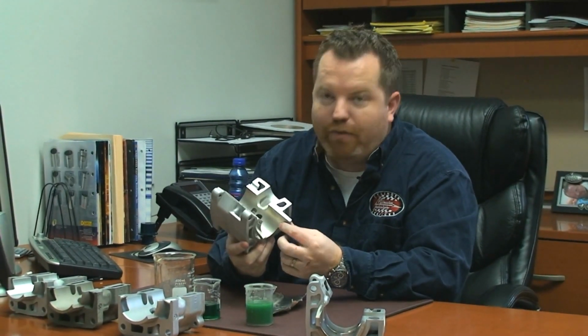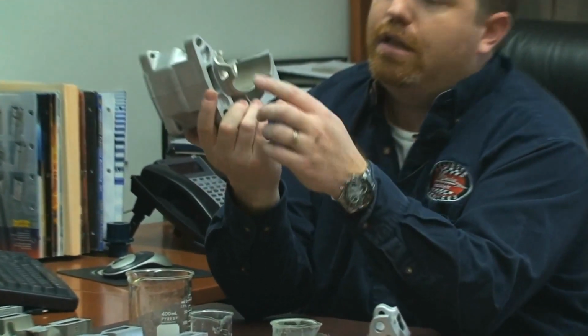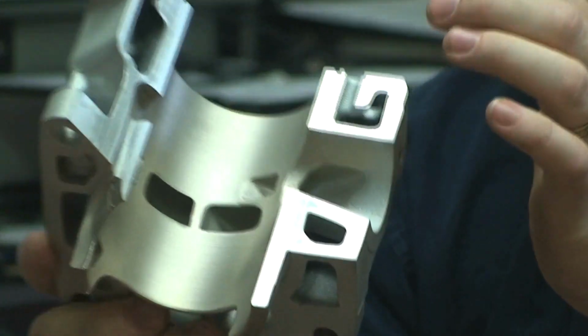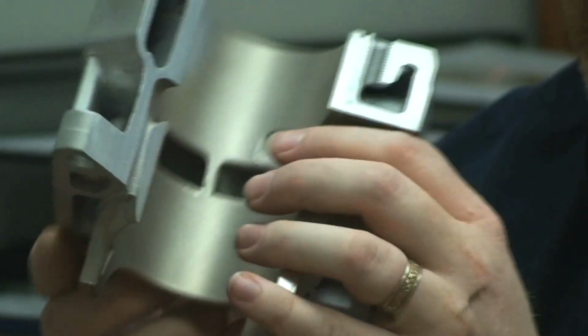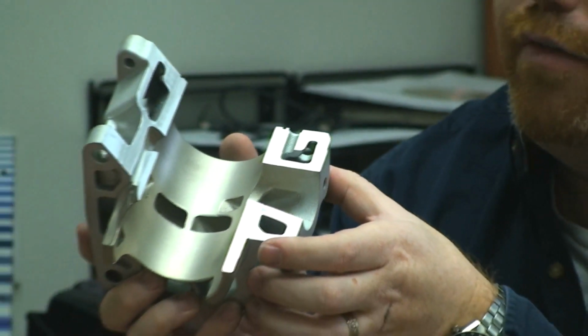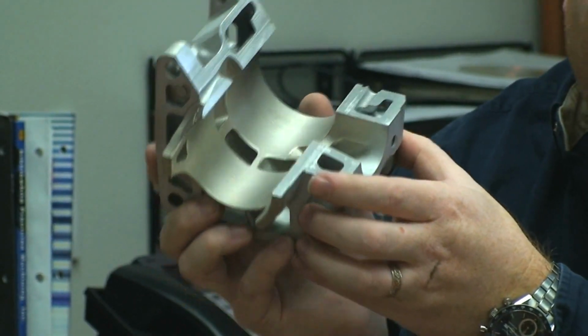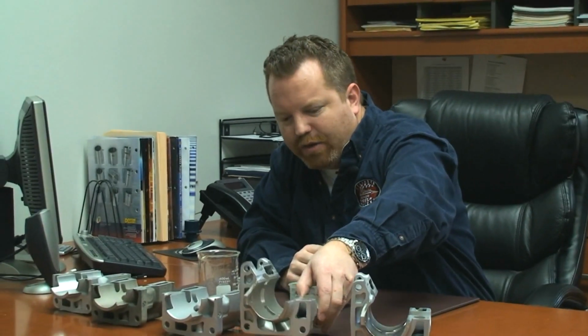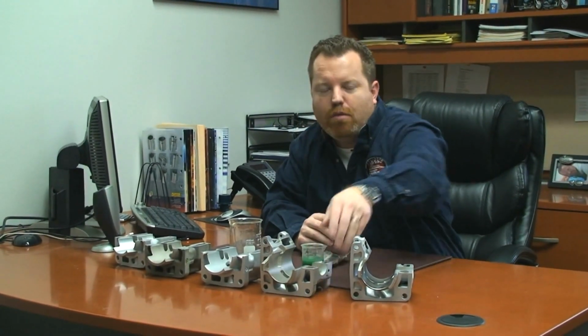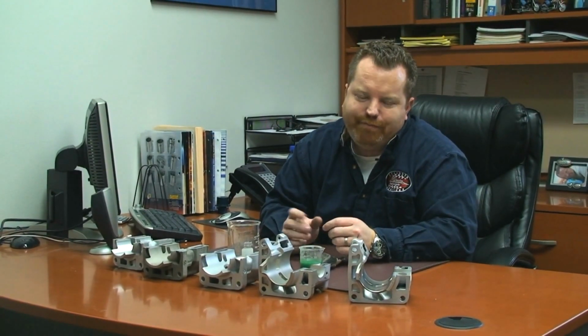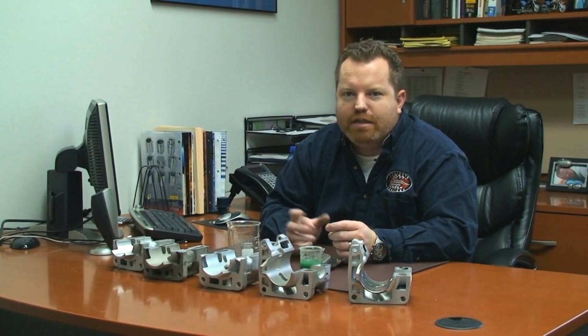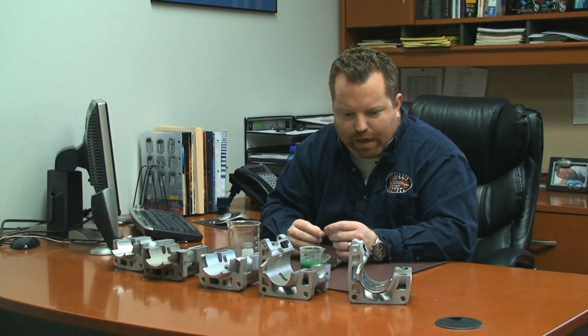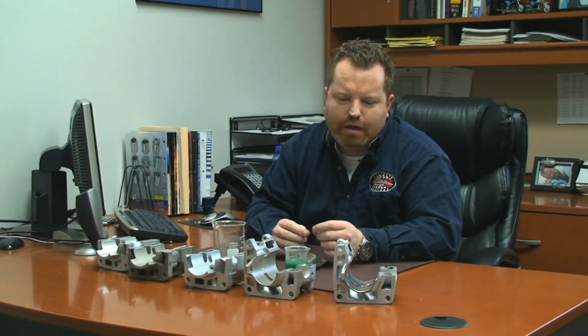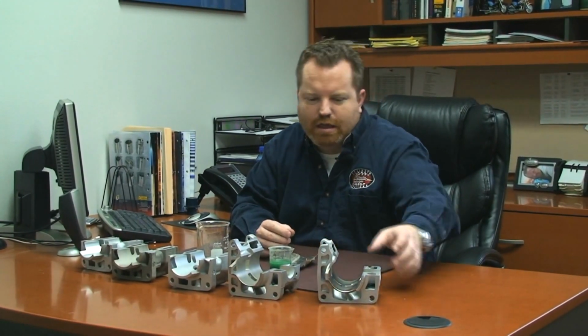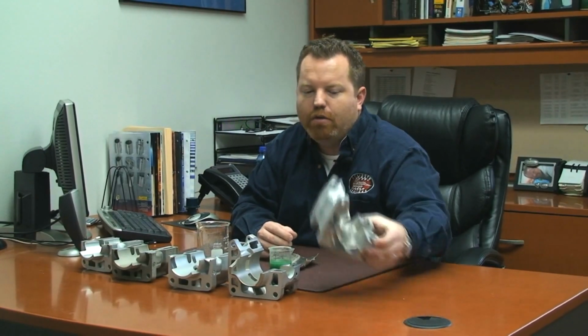This is what the cylinder looks like right before honing. You can see that the edges have been smoothed off, the cylinder's been cleaned, and it's ready to be diamond honed. The plating is pretty difficult to do. The honing is even more difficult. There are a lot of people that say they can hone Nikasil or nickel silicon carbide, but when you see what the finished product is, it's probably the hardest thing out of everything to do.